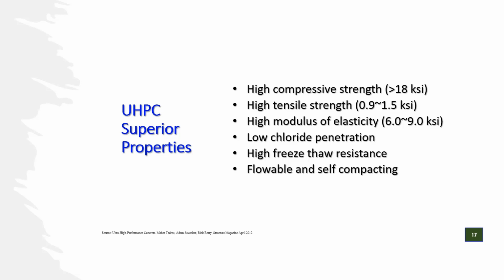As Dr. Azizinamini mentioned, we are using ultra high performance concrete for the 3D printing applications. Ultra high performance concrete has superior properties. According to the Federal Highway Administration, it has a very high compressive strength compared to other cementitious materials, usually more than 18 KSI. It has a very good tensile strength, usually between 0.9 to 1.5 KSI. It also provides a very good modulus of elasticity, between 6 to 9 KSI. Again, it has very low chloride penetration and very high resistance against freeze and thaw. On top of that, it's a flowable, self-compacting material.